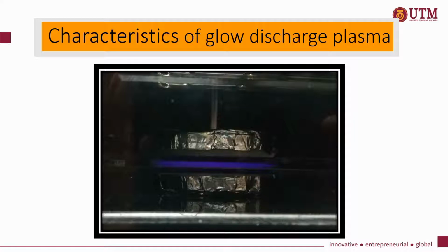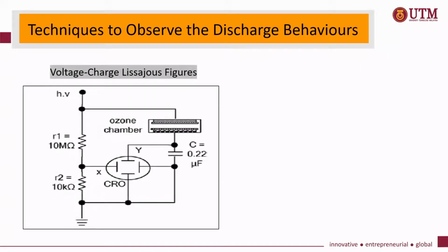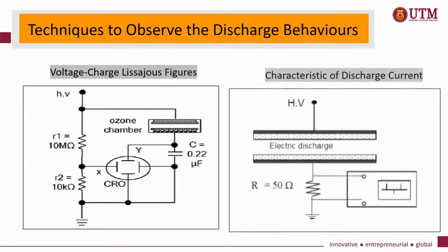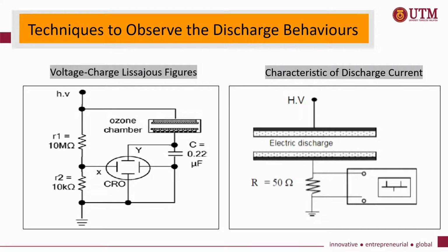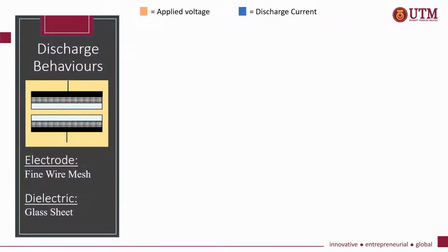So this is the visual observation of the typical glow discharge plasma, which is in purple color. Since visual observations are clearly inadequate for comparing the stability of the different discharges, 2 familiar discharge behavior techniques were adopted, which are the voltage-charge Lissajous figure and also the characteristic of the discharge current. The observation of the voltage and discharge current waveform were obtained and recorded.